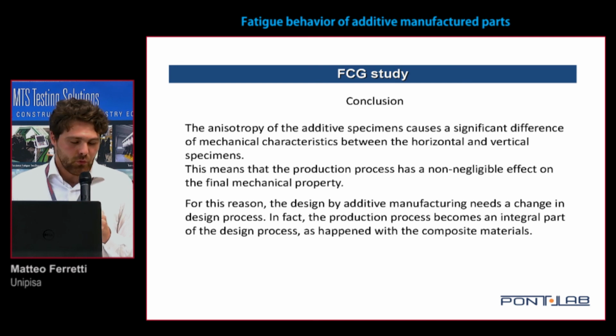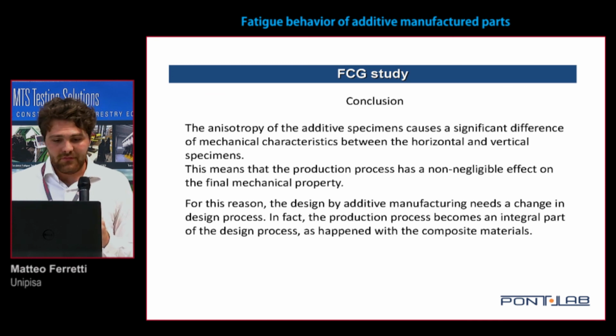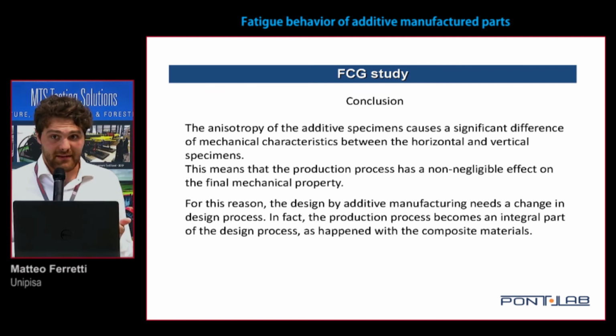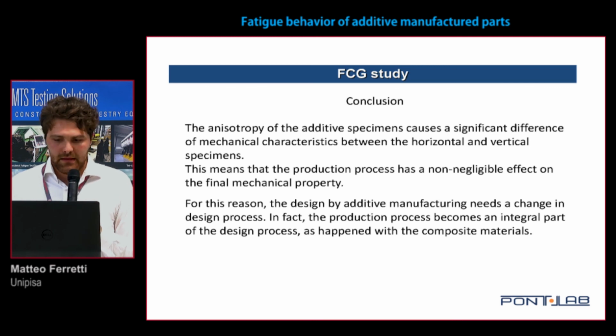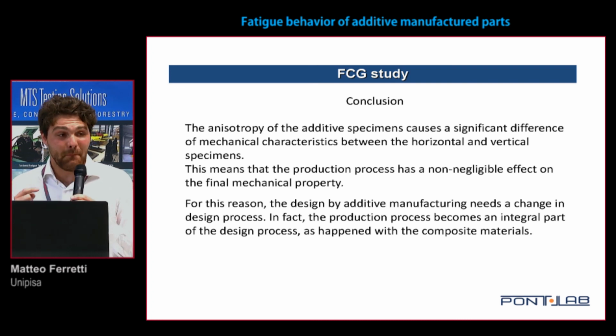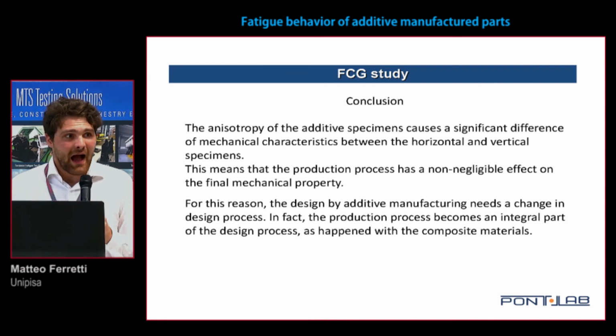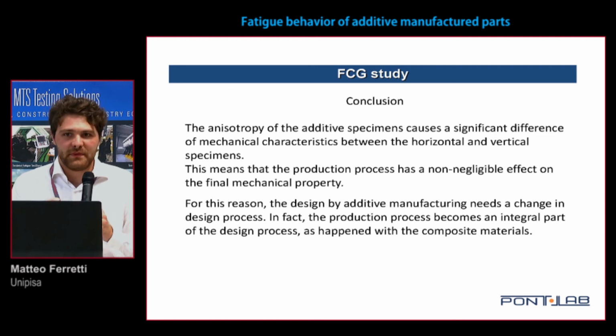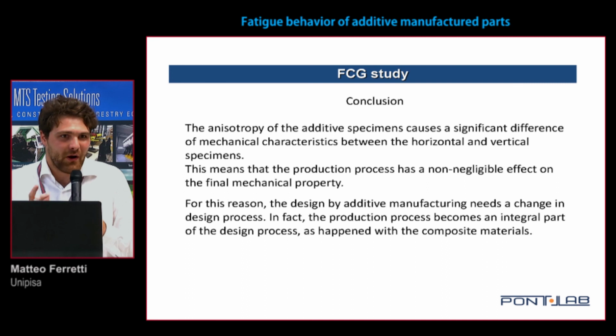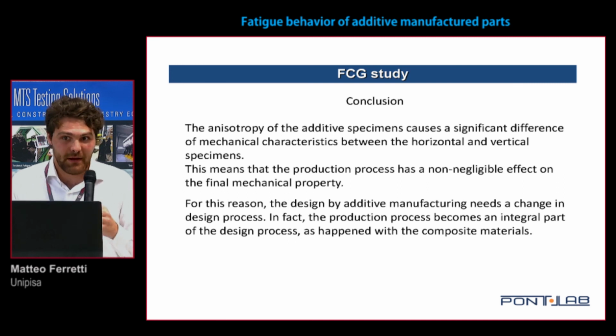And now I'm approaching the conclusion. The anisotropy of the additive specimens causes a significant difference in mechanical characteristics between the horizontal and vertical specimens. This means that the production process has a not negligible effect on the final mechanical properties. For these reasons, design for additive manufacturing needs a change in the design process. The production process, especially the building direction, becomes an integral part of the design process to obtain good results, or results similar to components produced by casting or another technology.